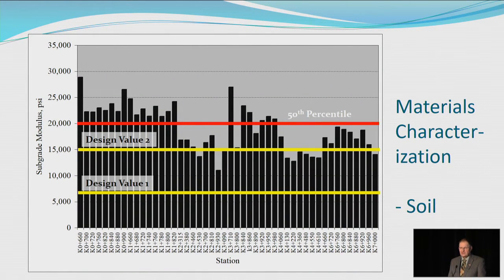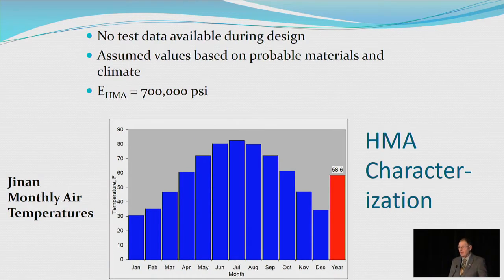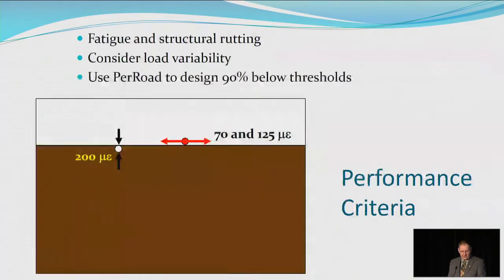We had materials characterization along the route that we had. It was approximately, how long was it? Somewhere around 3 miles. We built 5 sections. They varied in length, from half a mile to 3/4 of a mile, and the difference in length was because of bridges. We built between different bridges. We didn't have a lot of information on the HMA modulus. We did have weather conditions, and we were able to convert that into pavement temperatures. We were able to select an equivalent modulus for the HMA.